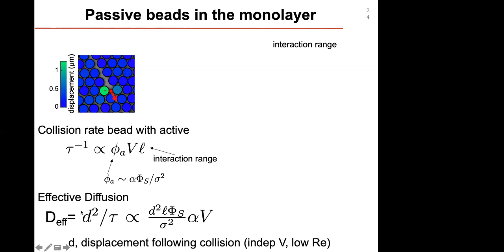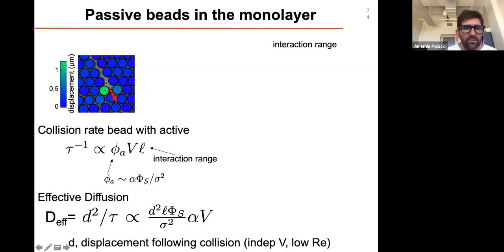Now, if we ask a very quick question. Yes, please. I'm just curious, are the active beads the same size as the passive ones? So the passive ones are 5 microns. The active ones here are like 1.5 to 2 microns. This is really a picture at scale, so you can see that the active particles are smaller. There are some practical reasons. If you put an active particle which is as big as a passive one, it's very hard to move without making a disclination. And disclinations are just so costly that they don't happen.